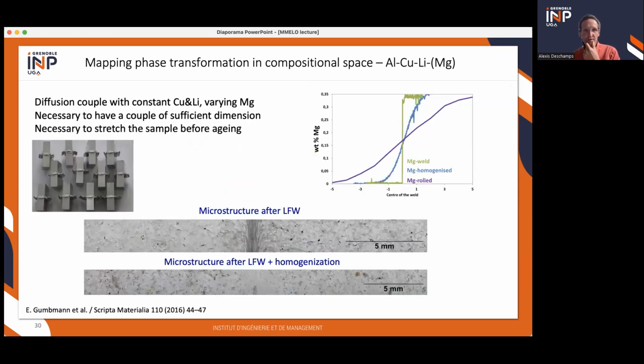You need to make diffusion couples. In aluminum, it's a bit tedious because you have this oxide layer, which makes it difficult to join two materials of different composition. So in this case, we used linear friction welding to make solid state welds with a planar interface between two compositions. Here one was with magnesium, the other one without. And then you make a homogenization treatment to get a composition gradient.